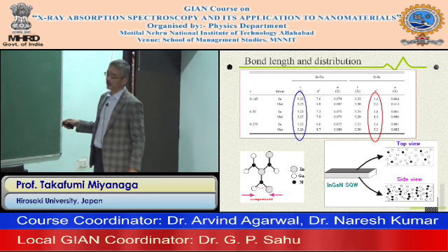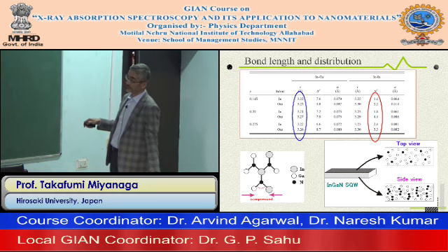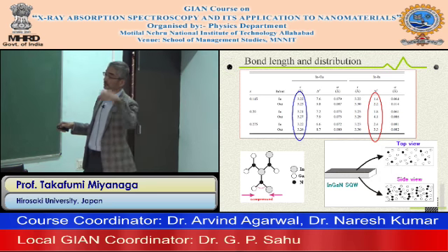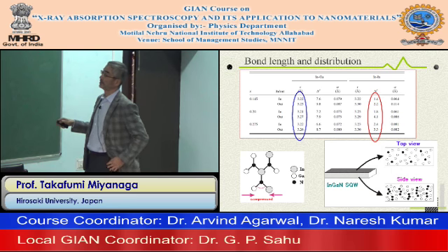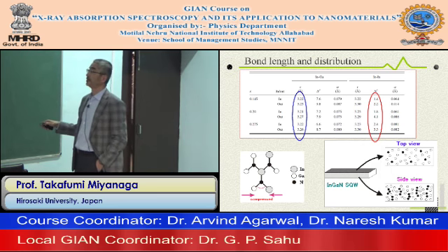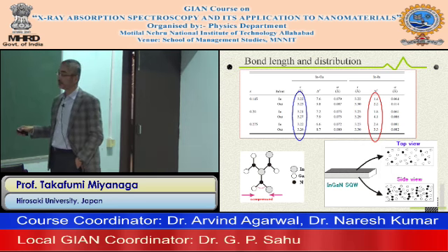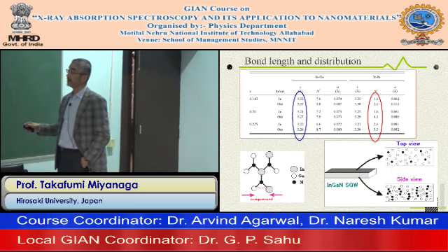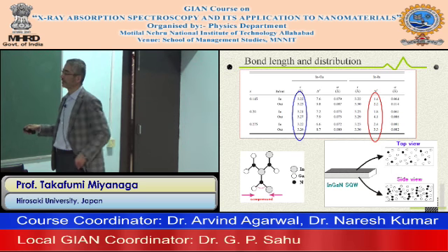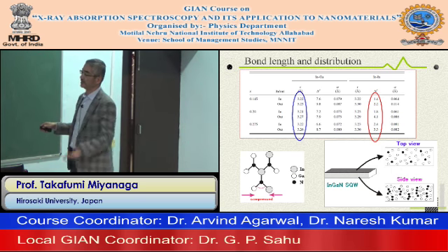Schematically, in the top view in the AB planes, indium atoms are distributed randomly. But in the horizontal view, the indium coordination is larger than in plane, so it means the indium gathers along the C-axis.